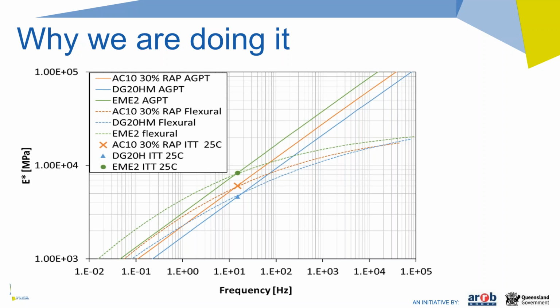So shown here is an EME2, a DG20HM, and an AC10 with some RAP in it, the EME2 being the top one. So we do a resilient modulus test, and we can get one point, and then from that we predict the modulus at different temperatures and frequencies using the Austroads equation. So if we use the Austroads method, that results in a straight line. So the straight lines on this chart represent the Austroads method. Because this is a log scale, it comes out as a straight line.